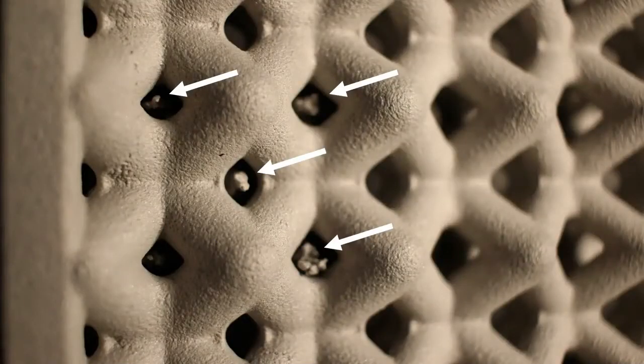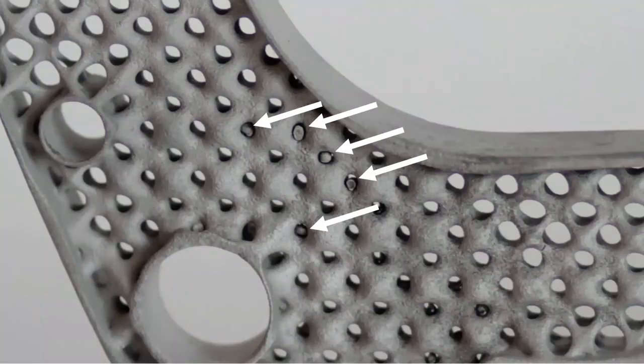What that looks like, and you can actually see this part afterwards when we go to questions: if you don't build up a shell of correct thickness, you're going to get a fracture, and metal is going to leak into that inadvertent mold cavity. And so what you end up with are these weird little nuggets of metal trapped in a lattice geometry like this. So this is one of the early seat frame prototypes where we didn't have those negative features properly sized, and so we got defective shell formation in those cavities, and got these little nuggets of metal in there.